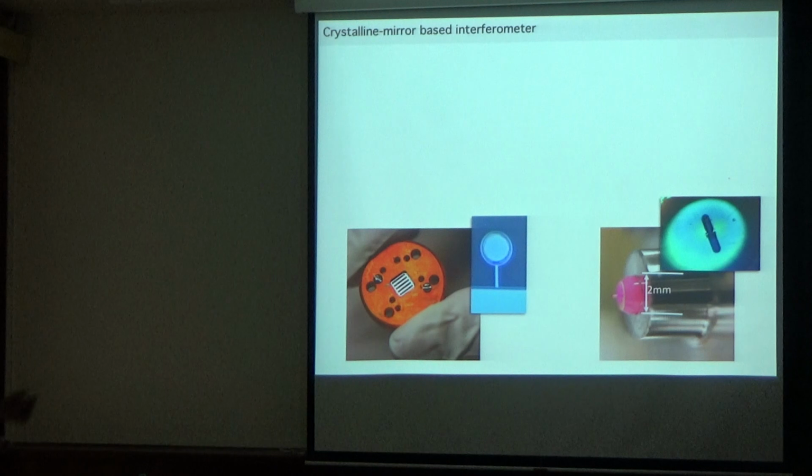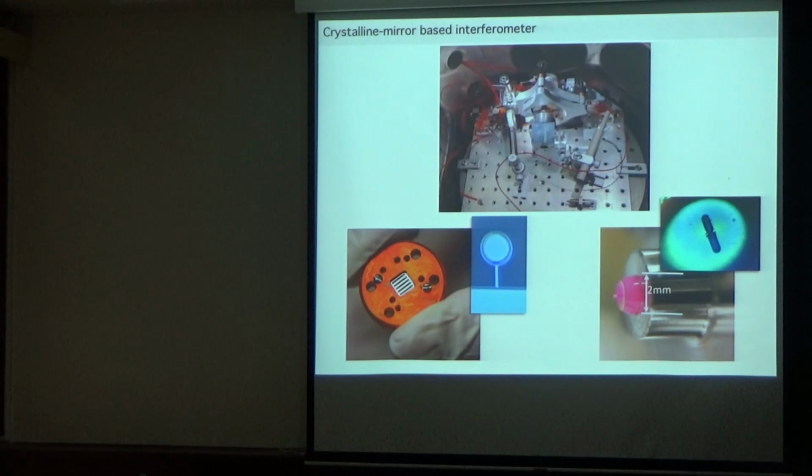So you have a fiber, the fiber's face is straight cleaved, it's got a dimple made with a CO2 laser, and it's coated with a standard tantala glass stack, which is the standard thing. And then the transmissivities of these two end mirrors are matched in such a way that the thermorefractive properties of this dominate, and that's already lower, basically because this is a highly transmissive mirror. And the entire system is operated in ultra high vacuum.